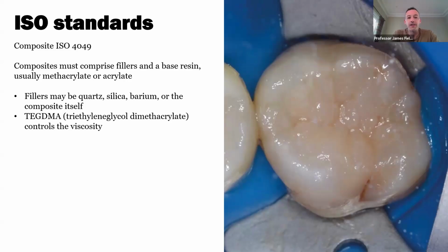There's something called triethylene glycol dimethacrylate, TEGDMA, which controls the viscosity. And when you go to the DS and other companies and look at all of their labs where they're making composites, a bit like a Willy Wonka showroom, you've got some of these materials which are very thin, and some of them are like treacle, very, very thick. And obviously what companies are doing is getting different ratios of these base resins together to give the composite a certain degree of sculptability, viscosity, all the properties that we see with it, self-leveling, etc., bulk cure. It's all a clever mixture of different base resins and fillers, filler types, filler shapes, and how they behave under loading, and when being cured. So it's a real science.